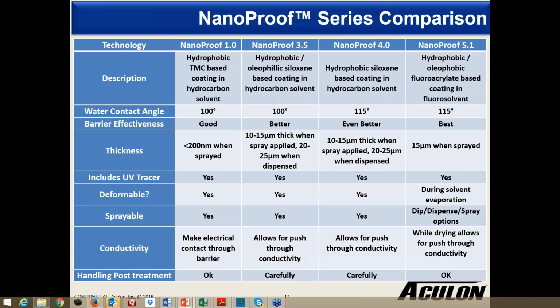However, this one ends up giving the best barrier properties, forms a physical barrier to shorting out of the contacts or ion migration. This one is still actually push through. You can still do push through conductivity, but you have to do it while the film's still wet. But all four of them are easy to use. I guess the last point there is for 5.1. After it's dry, you can be a little bit rougher with the handling compared to the other three.